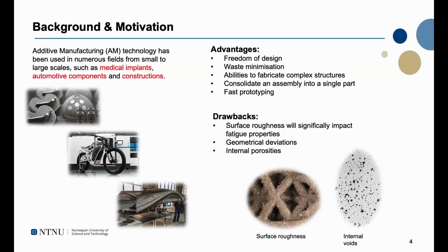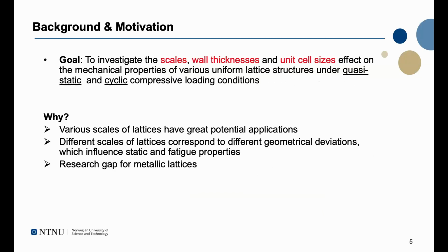But at the same time, it also has multiple drawbacks, such as surface roughness, which will significantly impact the fatigue properties. The fabricated specimens also have geometric deviations compared to the design files, and internal porosities which can affect the mechanical properties as well. So that's why the aim of this work is to investigate the scale, wall thickness, and unit cell size effects on the mechanical properties of lattice structures under both quasi-static and cyclic compressive loading conditions.